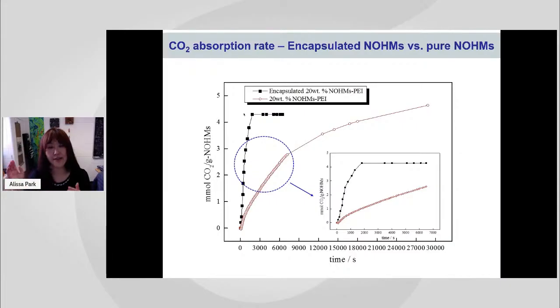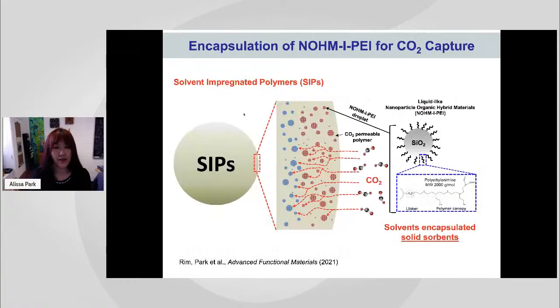The red data set is the NOHMs we started with, and the black data set is the one with encapsulation. As you can see, there's a much faster CO2 capture rate, and this is now getting relevant for us to achieve as a target. Now looking at that, I started thinking, well, can we even increase the interface area between gas and the liquid solvent we have? Next, we generated a material called solvent impregnated polymer.